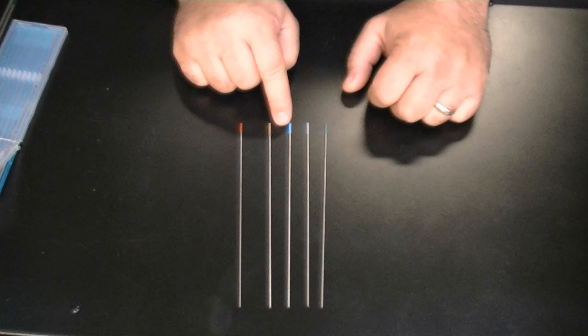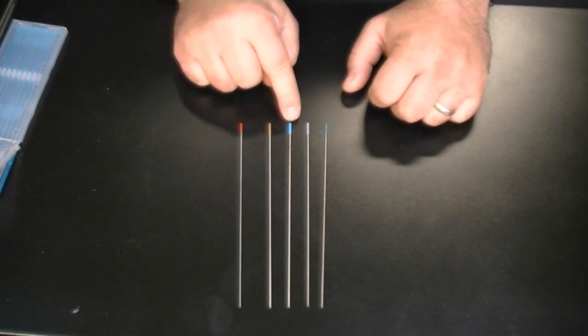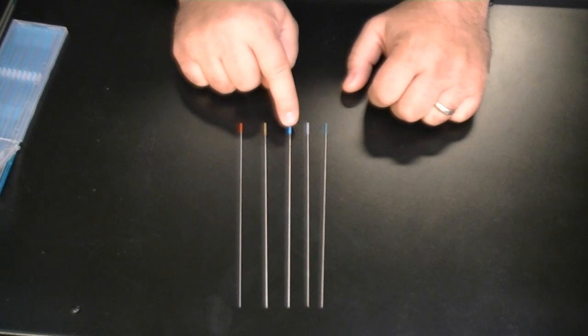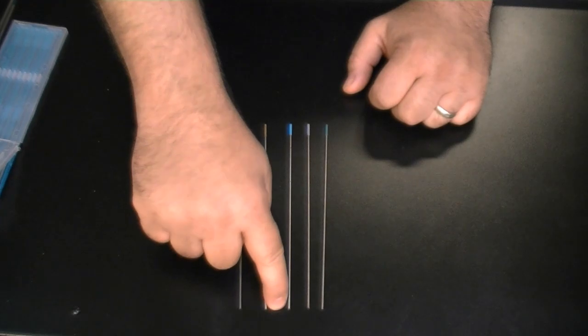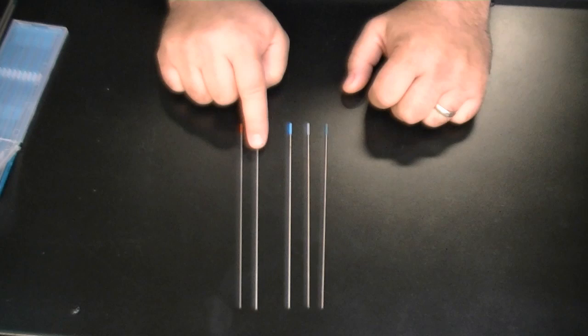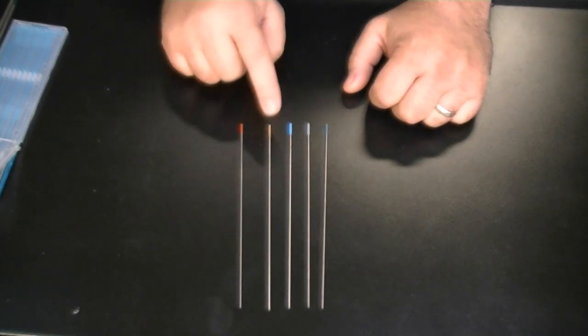The arc starts seem to be equivalent almost, if not a little bit better in some tests. Some people say it may not be quite as good, but overall this is a very good choice for replacement. We just said this was 2% lanthanated, indicated by the blue band. Some companies in some different countries, you're going to find a black band or some other color here, but usually it's going to be a blue band at the top to indicate 2%. 2% is not a bad choice. It is a very good, very stable welding electrode. Some people will say that there is a little bit more tip erosion with the 2%. I'm not sure why, but they do find that the 1.5 does seem to hold the point just a little bit better.